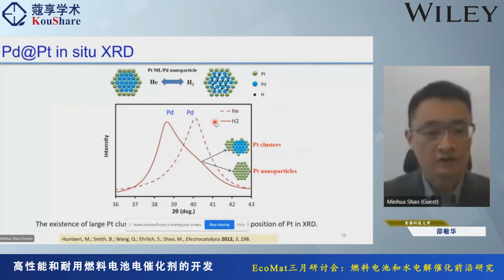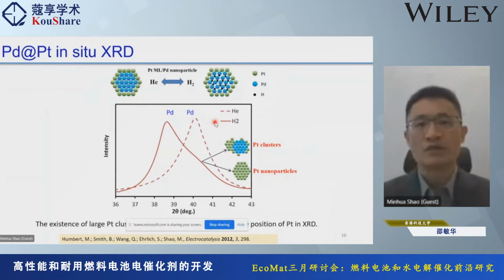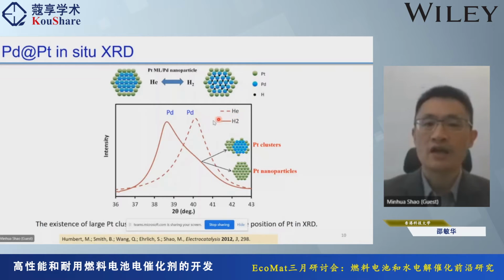This has actually been confirmed by our in situ X-ray diffraction. So the core-shell material that we synthesize has only one platinum monolayer supported on palladium nanoparticles, right? If you do these X-ray diffraction experiments in a regular atmosphere, for example helium or air, you only see one single peak, because palladium and platinum have very similar lattice constants, so you cannot distinguish them in X-ray diffraction. But if you do this in hydrogen, because palladium is a good hydrogen storage material, it absorbs a lot of hydrogen, so that will cause a lattice expansion.